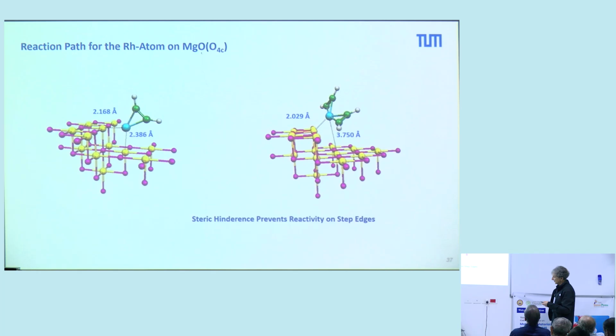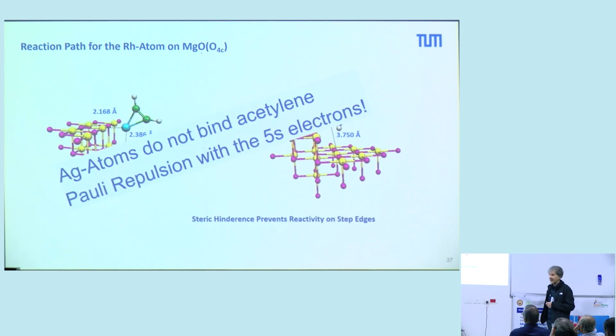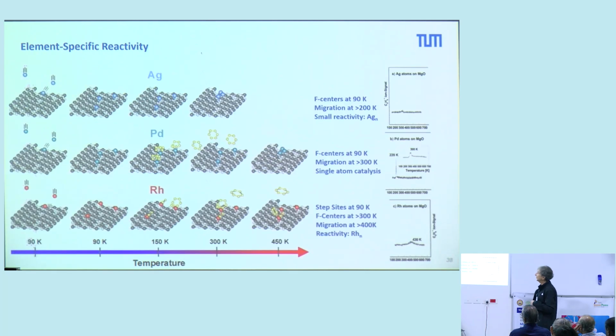So you can tune the chemical reactivity. For rhodium atoms, they are stable at these edge sites. And there is a steric hindrance for the reaction to take place. That means single rhodium atoms will not be active. And silver atoms neither, because we have a Pauli repulsion and we cannot absorb this molecule. So if you interpret these reactivities, you have to know the dynamics and you have to know the chemical environment. This is very important if you talk about single atom catalysis.